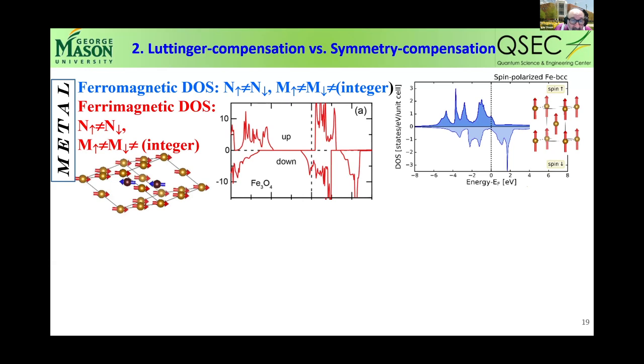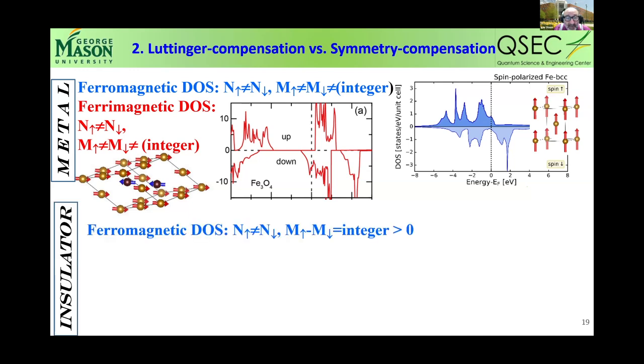Or compare that with another material, which is Fe3O4, the classical magnetite. It is actually what we call a half metal. So there is a gap in one spin channel, and because of that, the density of states in the up channel has to integrate to an integer number. And then again, by charge compensation, even though the Fermi level in the down band is metallic, it still has to encompass an integer number of spins. So that means now that the net magnetization doesn't have to be 0, but it has to be an integer. That's what I call this Luttinger compensation.